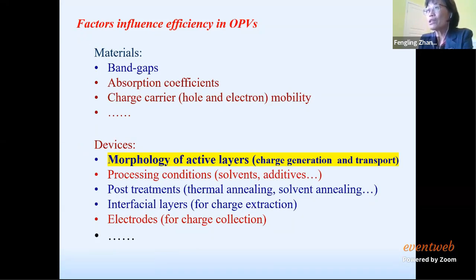But even if the material is good enough, we still need to optimize the conditions to make a device. These processing conditions include temperature, solvent, and additive. Nowadays, the most popular standard processing conditions always use some kind of additive to adjust the drying time, so the materials have time to mix with each other. So it depends on the material. For post-treatment, some materials need to be treated with thermal annealing or solvent annealing to further manipulate the morphology.